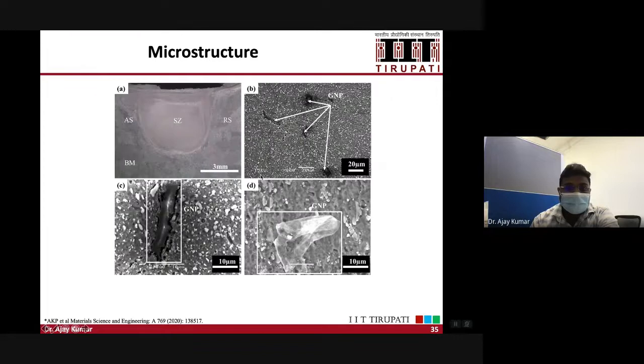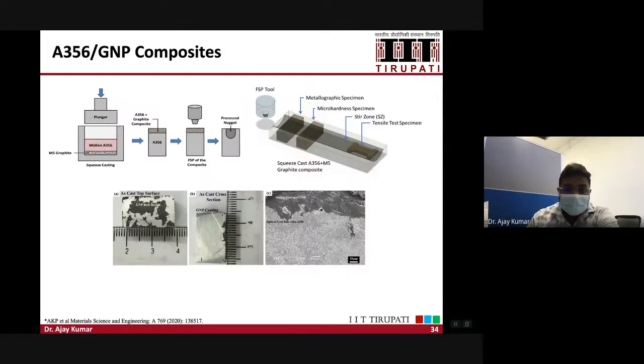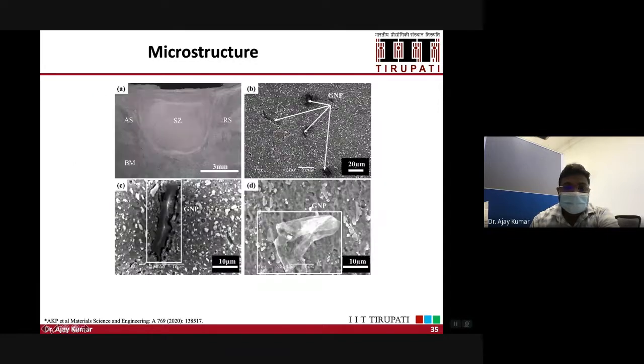So let me show you the microstructure. When we applied this process, the first step was squeeze casting, where we produced the coating of GNP on the A356 alloy. So this is like a surface composite. And then we carried out the FSP process on the sample. And as you know, this is the nugget zone after the process. So this is the composite zone here.